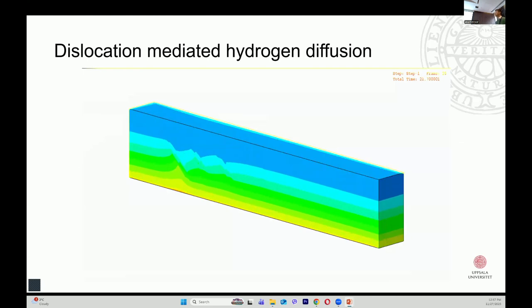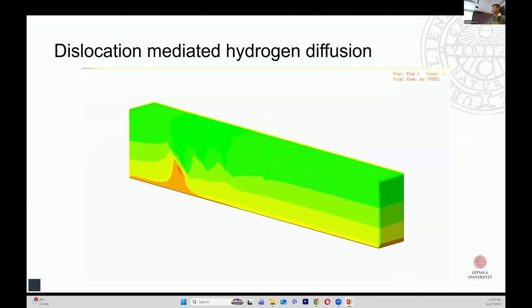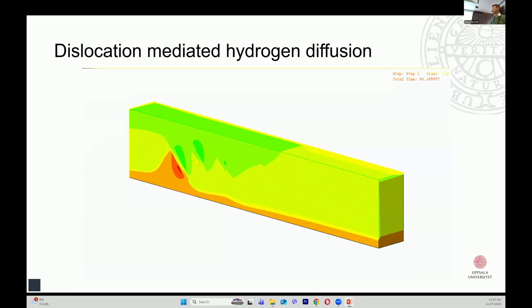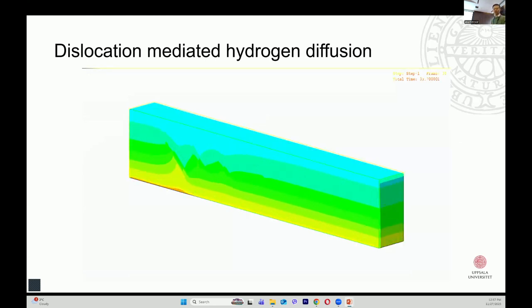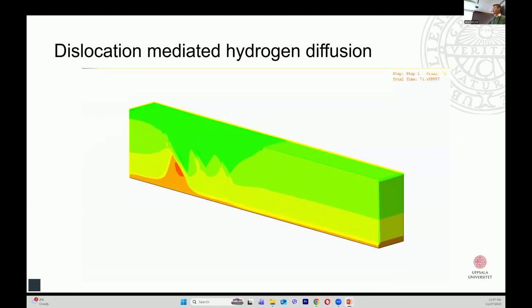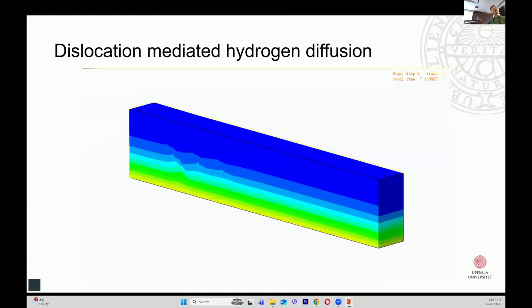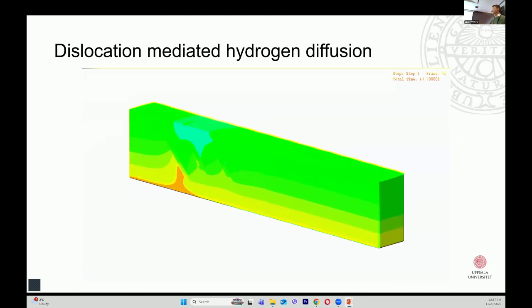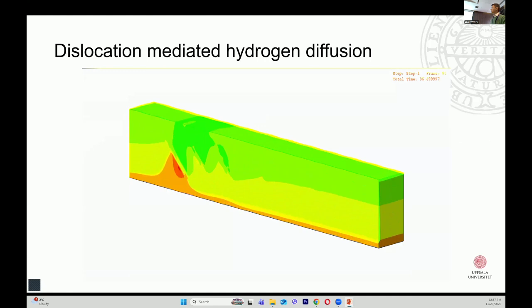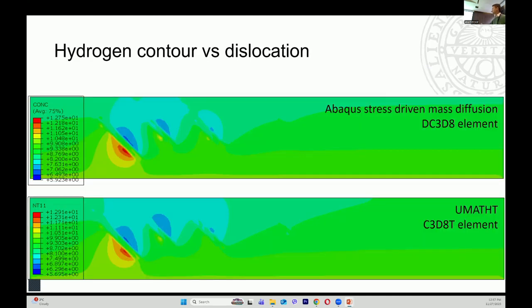And this is our simulated diffusion profile. And apparently the diffusion is non-uniform. And this is in contrast to the uniform profile I presented earlier. And the reason is exactly that we considered the discrete dislocations, and their stress field directly governs the hydrogen distribution without explicitly considering any trapping effect. And this is done in Abaqus with a user-defined subroutine. And we also compared our results to the Abaqus embedded diffusion, which the previous presenter, I think, used this platform. And we can see good agreement, which adds to our confidence level.